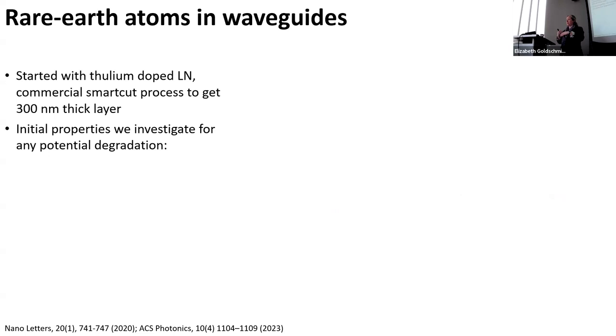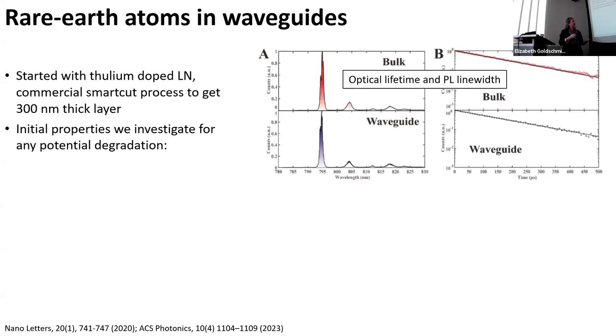The way that we get our thin film lithium niobate is the smart cut process. We have bulk thulium-doped lithium niobate, they send helium atoms at it to make a damage layer, and they peel off a layer of lithium niobate and then put it on some substrate. We wanted to make sure that that plus our nanofabrication techniques didn't kill the properties of the thulium, so we did some initial measurements of these properties. We looked at the photoluminescence, the lifetime of it, and it looked fine.